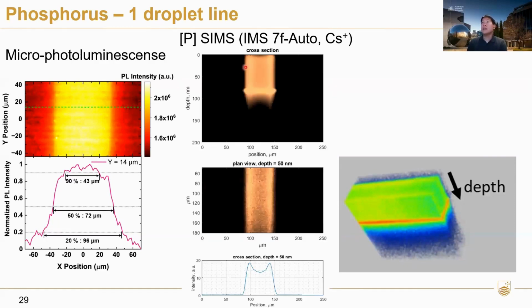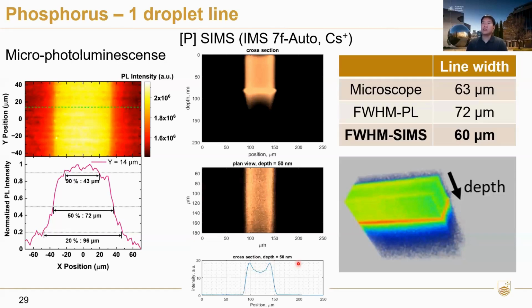If we do the same thing, we can plot the cross-section of the image, and we can see the pile-up here again very clearly, with a bit of indiffusion into the crystalline silicon. We do the same thing with a plan view, showing good uniformity in terms of width. And if we plot the cross-section, then we can extract the full width half maximum as well. Again, they're all in a very close range of about 60 to 70 microns. So good agreement between SIMS, PL, and the optical microscope. So that's very comforting to know.